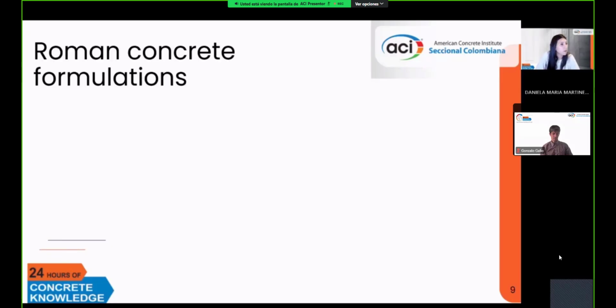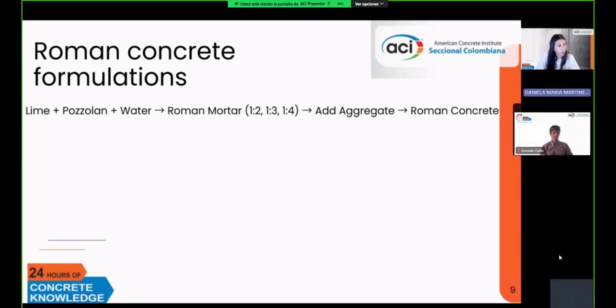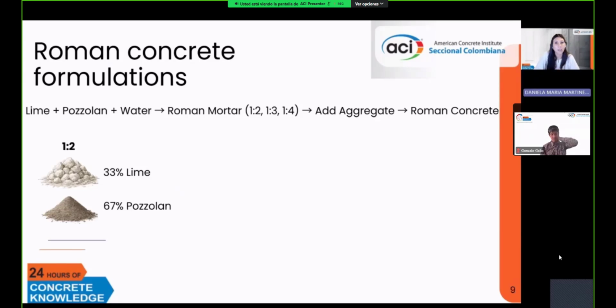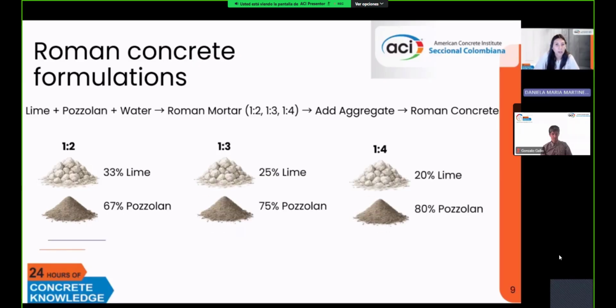Now, since Roman concrete was not made uniformly, we needed to establish certain parameters to determine what mixes we were going to use to compare to those mixes that we typically use in modern concrete. So we basically started with the reaction of our raw materials that form the Roman mortar, and then we add aggregates and we obtain Roman concrete. The Roman mortar formulations we draw from different reports and studies in literature, and we determined that we were going to model 3 types of Roman mortars usually found in literature from Roman concrete reconstruction. The ratios were 1:2, 1:3, and 1:4, and these vary depending on the ratios of lime to pozzolan. These formulations form the basis of our environmental comparison.